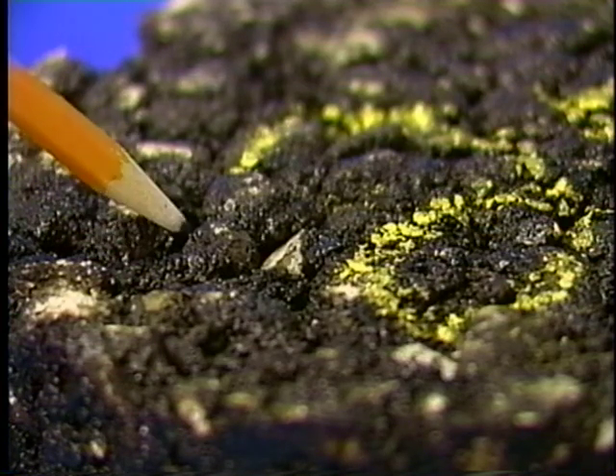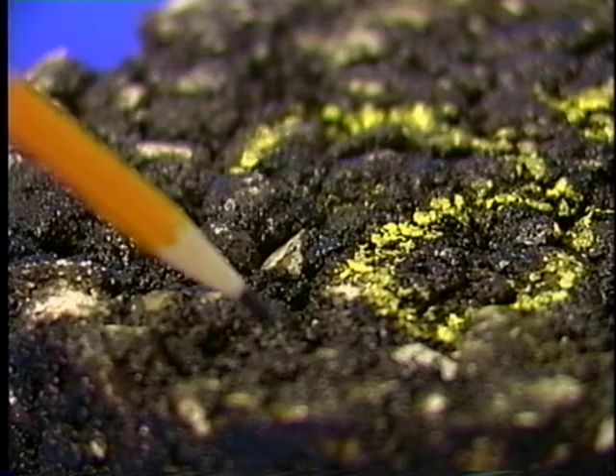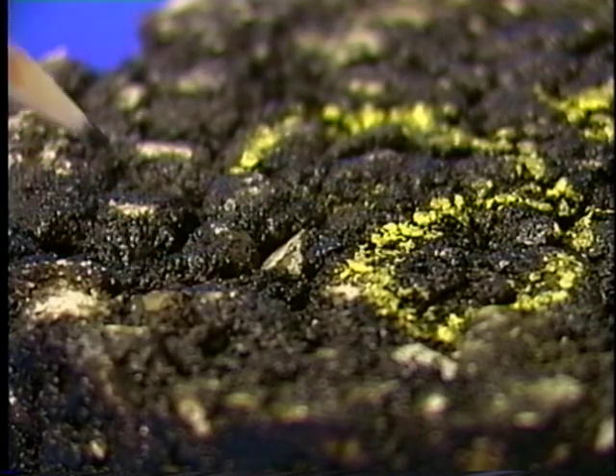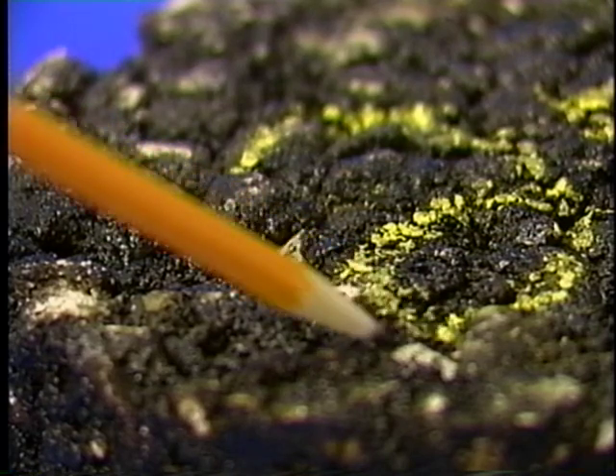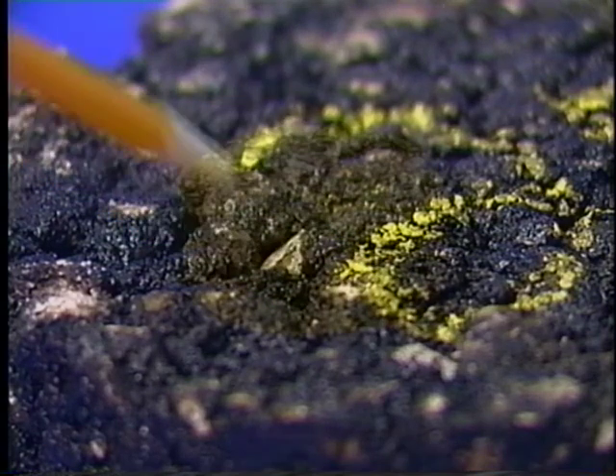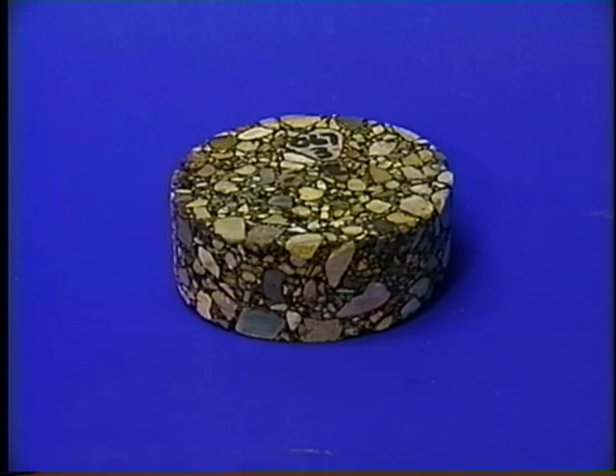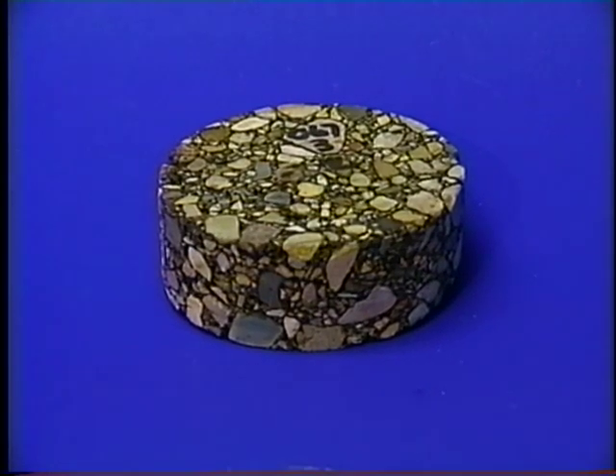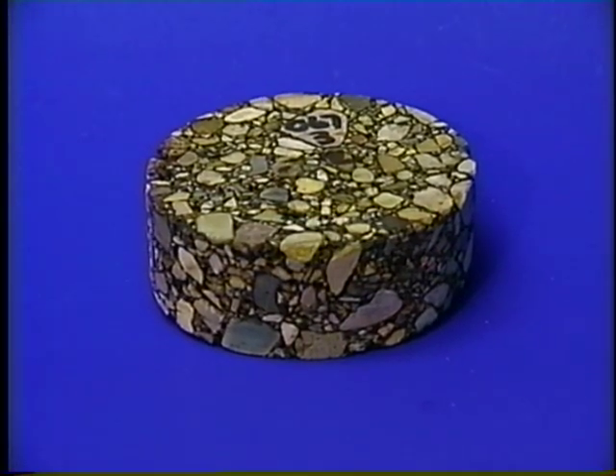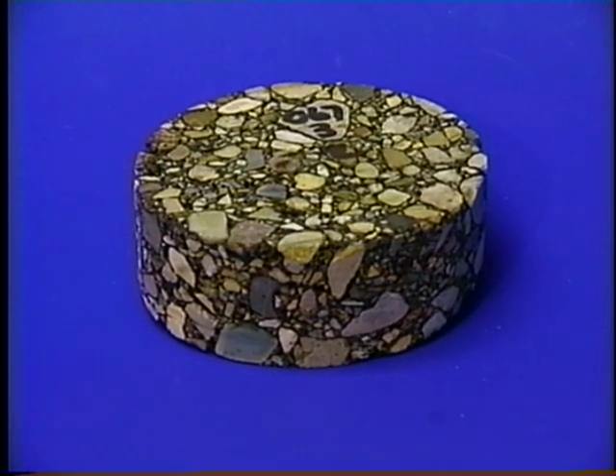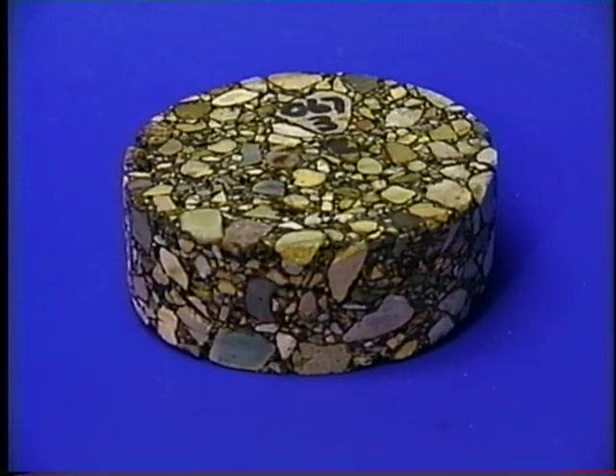Air voids are defined as the total volume of the small pockets of air between the coated aggregate particles in a compacted HMA mixture. Air voids are directly related to the permeability of a mixture. As the air voids increase, the permeability of the sample will increase. Air voids are expressed as a percent of the total volume of the compacted mixture.